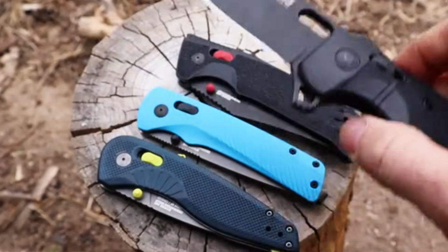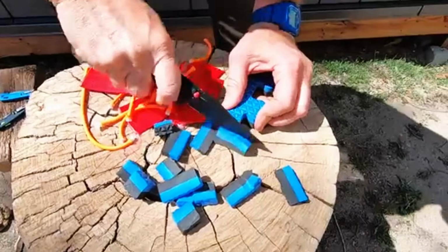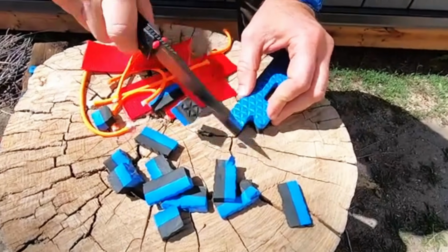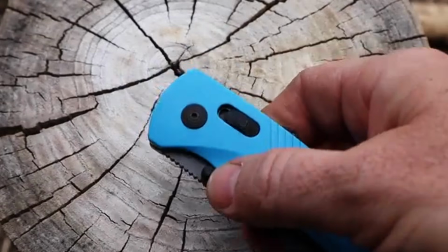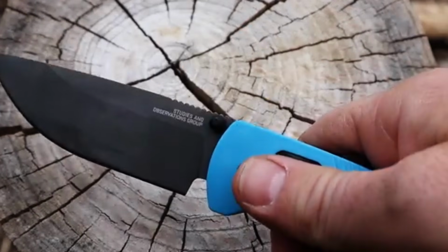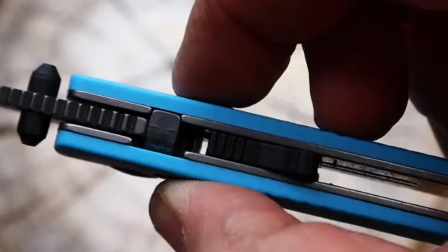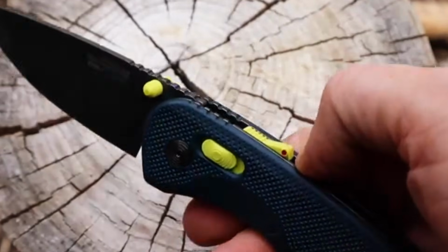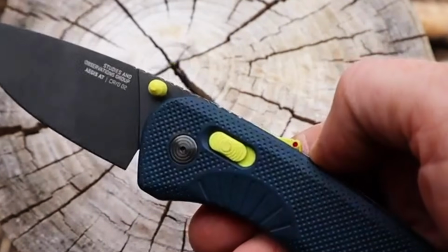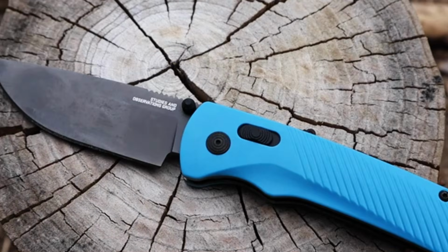Not as fast as 1095, but faster than most buyers expect from a steel marketed as semi-stainless. In my corrosion test, D2 showed surface spotting at 14 hours of saltwater exposure. 1095 showed it at 8 hours. The gap is real, but it is not the gap that semi-stainless implies. The problem is what you give up to get it.